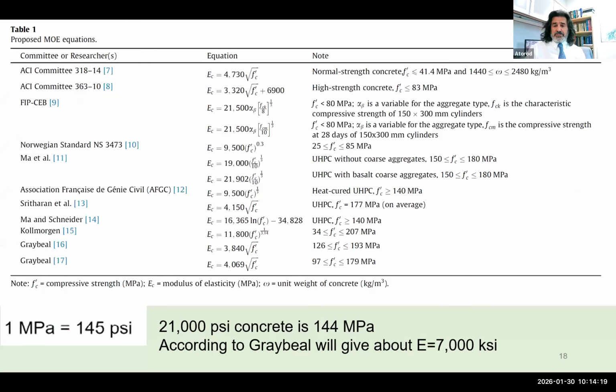One of the main aspects of the UHPC is that its modulus of elasticity is very high. Now, if you want to apply it to a building, you can actually measure the modulus of elasticity. And if you measure it, it's going to be higher than some of these equations that are around will give you. I mean, we are talking about a modulus of elasticity of like 9,000 KSI.